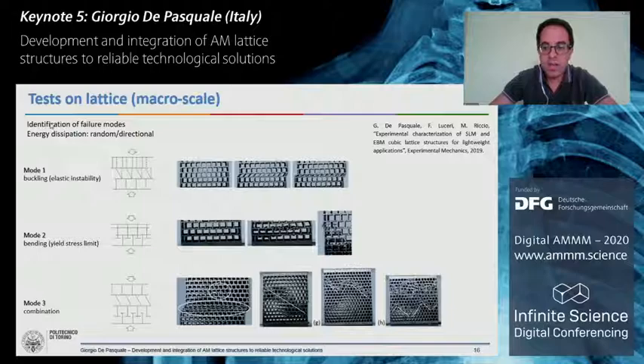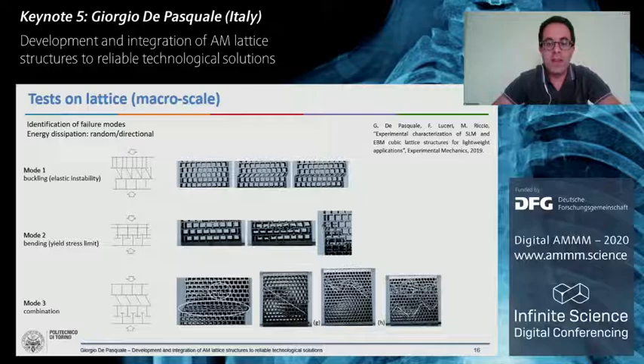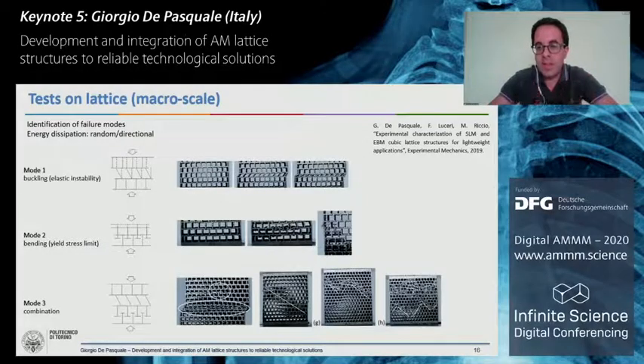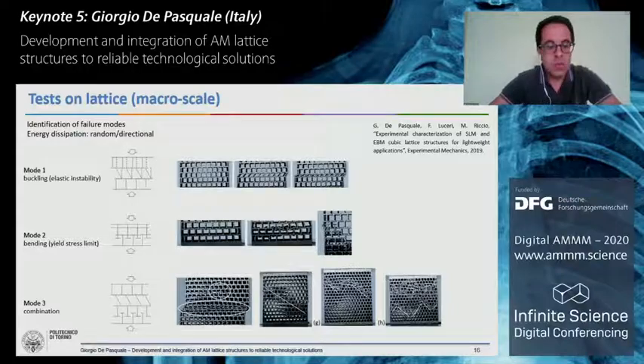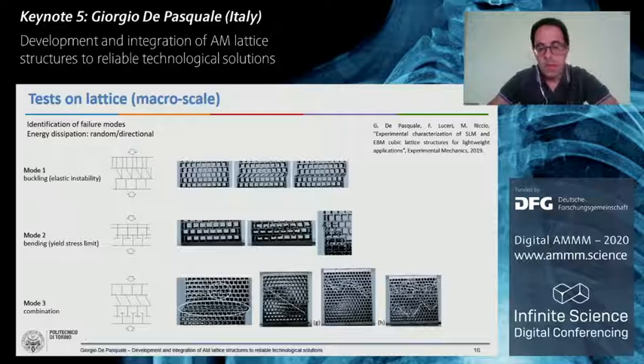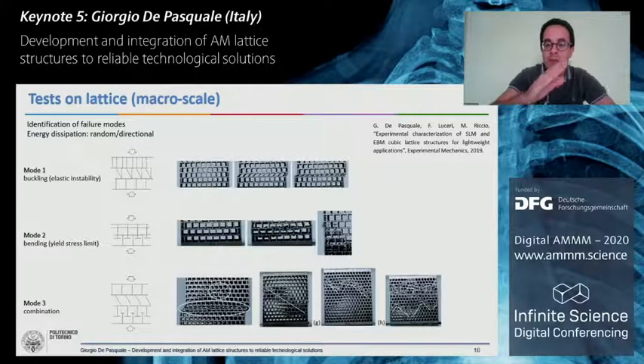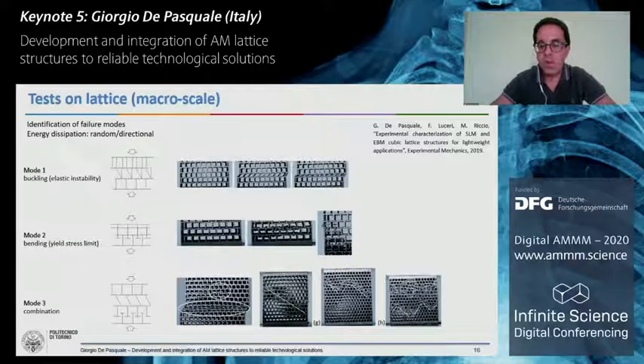Another important result from our tests is the mode of failure. In this specific sample, we observed, for instance, three main failure modes. Mode 1 is associated with a buckling behavior, so instability behavior of vertical struts. In mode 2, we have a bending behavior of horizontal struts, so plastic failure. And mode 3 is a combination of mode 1 and mode 2. Here we can also see that the line of fracture of our sample follows the shape of the cell. So in some way we are also able to modulate the direction and the way of cracking of our sample by changing the shape and the distribution of cells in space.